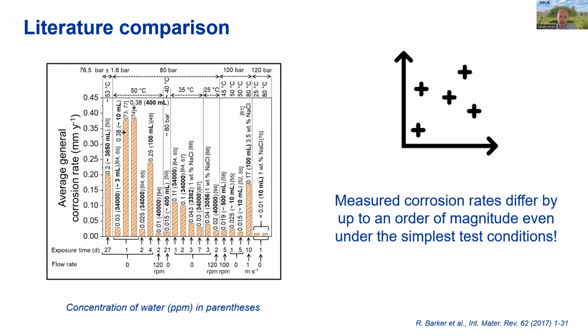We did a very systematic review of published corrosion rate data in the literature. And really, the bottom line is that there is no consensus whatsoever. There is a real reproducibility problem in the measured corrosion rates that are reported by different laboratories, and even between the same laboratories in some cases. So even under the simplest conditions where the only impurity in the CO2 is water, the measured corrosion rates can differ by up to an order of magnitude, a factor of 10. So, you know, this makes it really difficult to compare results from different laboratories or to have any confidence in the reported data that are published in the literature.